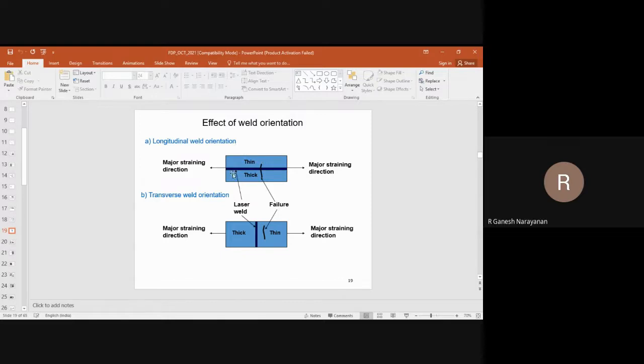Here, weld orientation means you take a rectangular sheet, thin sheet and thick sheet, and you weld. Simple. And weld orientation here means that in the longitudinal weld, the weld is along the loading direction or major straining direction. Here it is perpendicular. Simply to tell. Here you can also have 45 degree, 60 degree, 80 degree. Everything is possible.